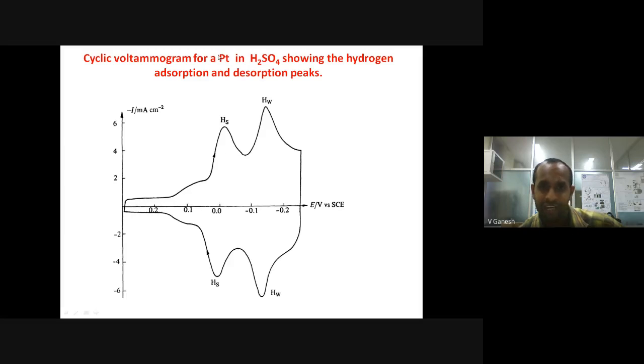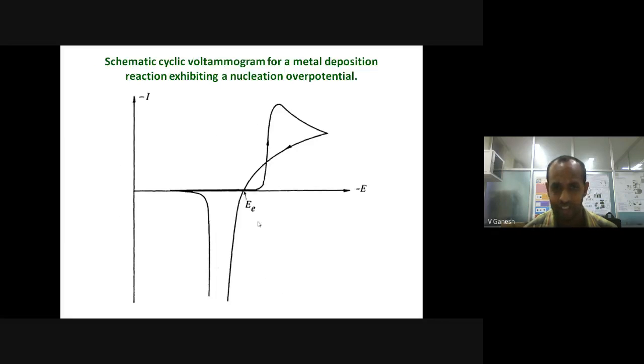The typical behavior to assess the cleanliness of platinum electrode is by observing this kind of peaks. Okay, so this suggests that if you do a cyclic voltammetry experiment in sulfuric acid, you would typically observe hydrogen adsorption and desorption peak on platinum electrode. By integrating the charge associated with this peak, one can assess the surface area of the platinum electrode. Maybe I will talk about this when we discuss electrocatalysis.